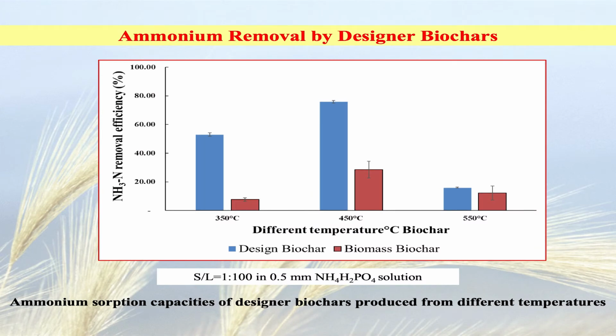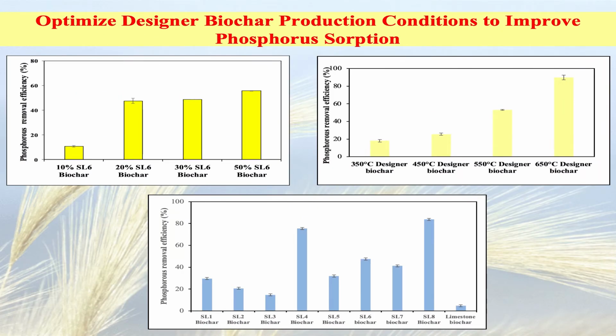Before I mentioned, biochar mostly can absorb ammonia. But we find our designed biochar actually removes ammonia better. So this means the design improves the ammonia absorption. Also, most importantly, we find that phosphate removal by our designed biochar is significantly increased. So that's why we optimize the designed biochar production conditions. For example, we're using different pyrolysis temperatures, different lime sludge, also different lime sludge application rates. The purpose is to make the most efficient and cost-effective designed biochar. If you're interested, later in the afternoon poster session, my student will show you more detail on how to modify and optimize the conditions to get the best designed biochar.